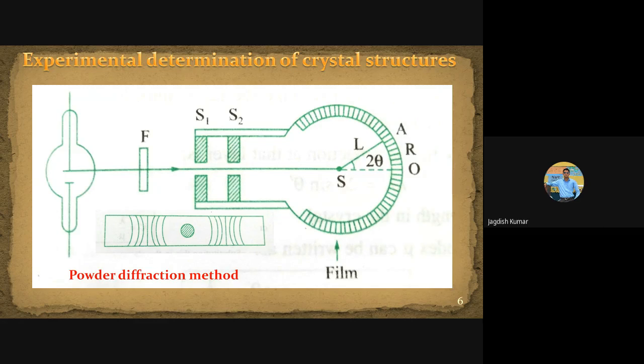And then finally there are a lot of things again. Even suppose atomic positions are tentative, we didn't know the exact atomic positions, we fixed them, then our X-ray peaks may not match. So we also try to move the atomic positions with the help of the software in such a way that the atomic positions which best reproduce the experimental pattern are considered the better ones. That is how a lot of hit and trial, a lot of smart guesswork goes into fitting the Rietveld refinement pattern for any X-ray data.